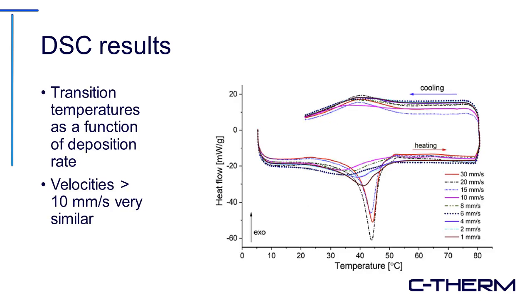Using DSC, you can also achieve examination of different velocities of manufacturing and take a look at how that affects the thermal properties. So this is looking at manufacturing velocities ranging from 1 millimeter per second all the way up to 30 millimeters per second. And velocities greater than 10 millimeters per second all are behaving quite similarly. So below that, the properties are quite sensitive, and above that, it doesn't seem to have much of an effect on the overall behavior of the alloy.